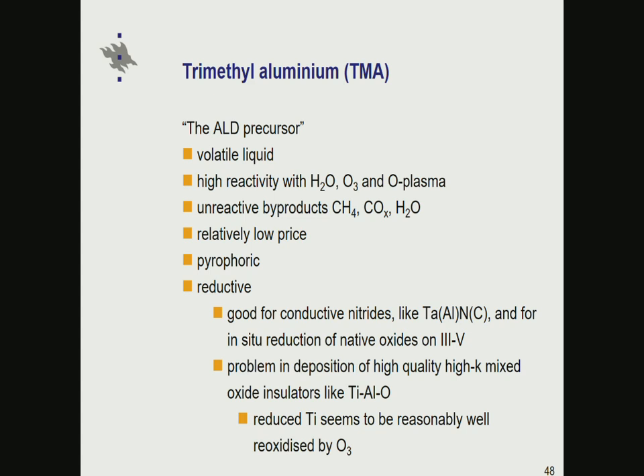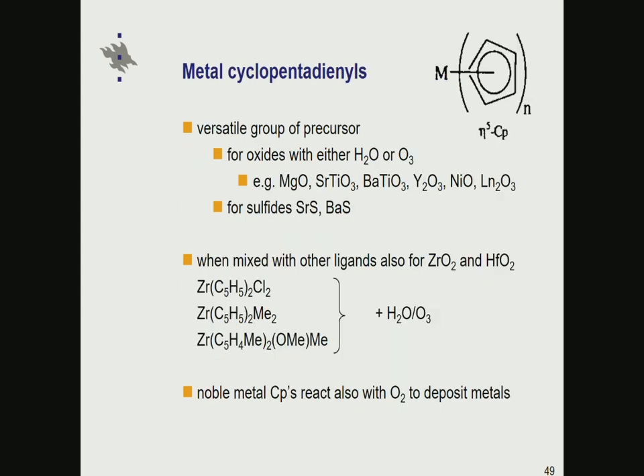The problem is if you want to make high quality mixed high-K materials where you are mixing aluminum, especially with oxides which aren't quite readily reduced, like titanium for example. So TMA is to some extent reducing titanium, and while doing that it's creating defects, which then deteriorate the insulating properties. But this can be compensated, at least reasonably well, by using the strong oxidizer ozone in the process.